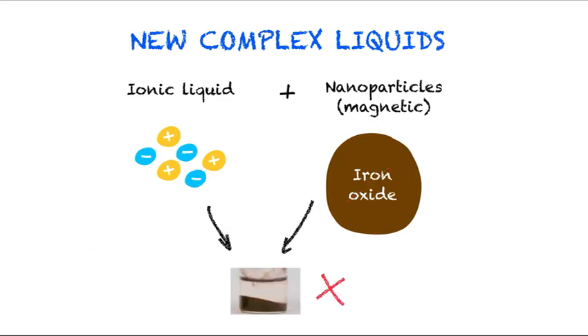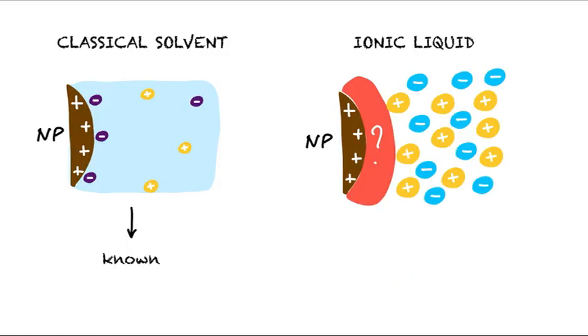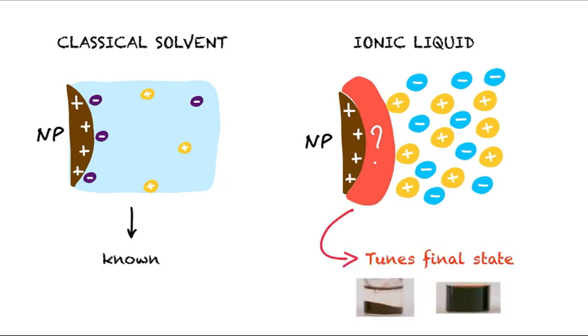If you mix both systems, you will finish with powder under a liquid in many cases, which you don't want for the project in thermoelectricity. You need a homogeneous liquid. So in a classical solvent, the nanoparticle-solvent interface has been widely studied and is known. This is not the case in ionic liquids. However, this region, the red one, controls the resulting dispersion state that you obtain, and it can be tuned.